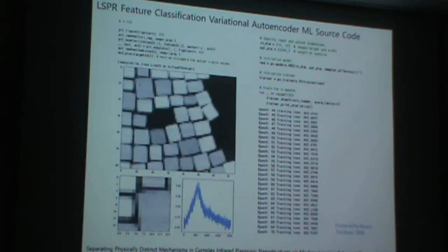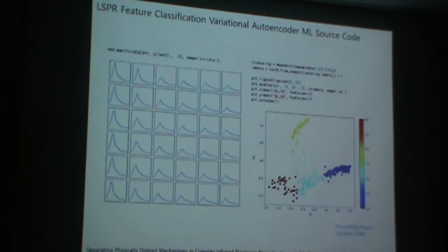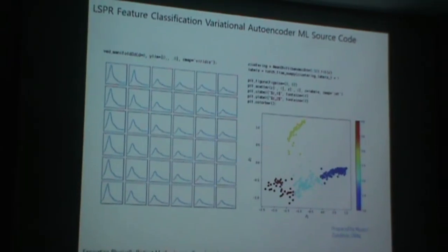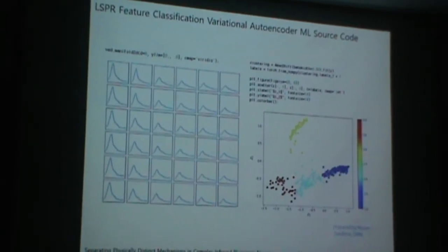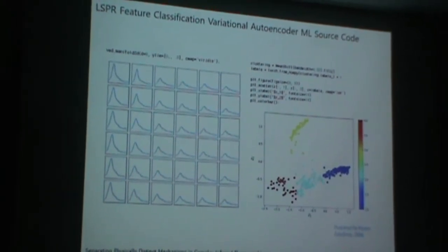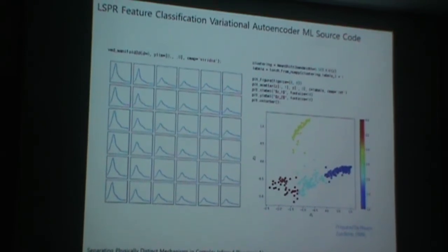We undergo variational autoencoder training processes with multiple iterations. What we can do is then start auto-generating various spectral features, which is pretty much dictated by two dimensions. One would be the intensity of the electron energy loss spectroscopy, and the second would be the peak position of such plasmonic modes. Then it is mapped out in latent space, as mentioned, Z1, Z2, that will be the intensity and the location of the peak.